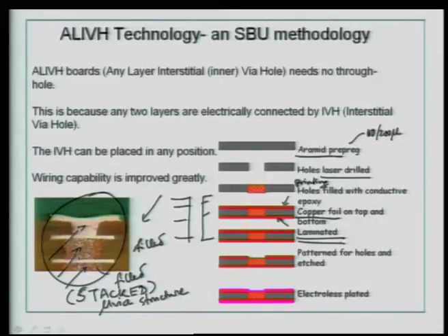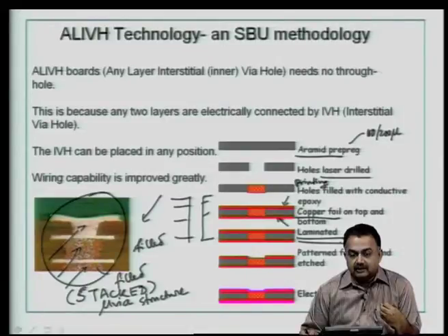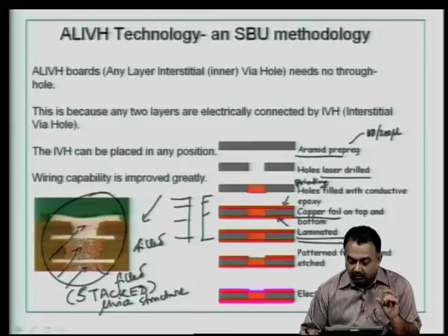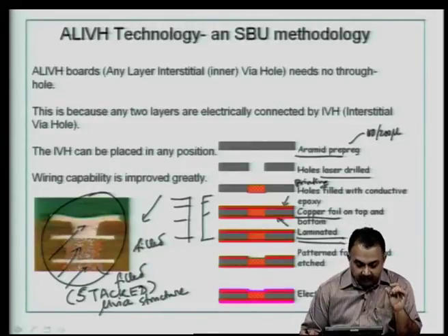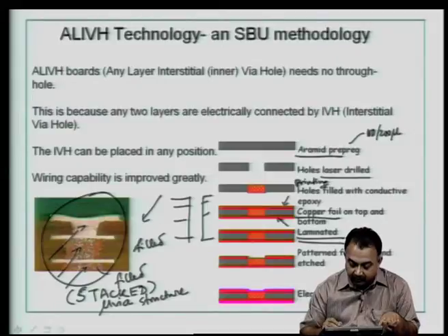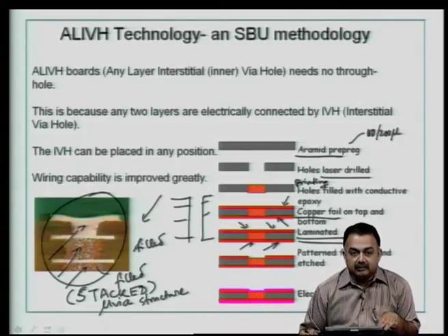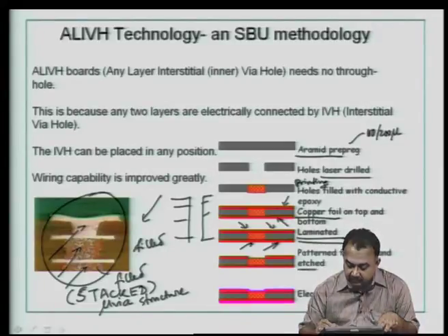Okay. So, here you want to cure the material, and you are also using the pre-preg material's physical properties, because it contains some kind of a solvent. It is a B stage resin, as you know, and then you have the uncured conductive paste that has been dispensed in the hole wall. Now, all of these entities together are laminated. Now, you get a very good bonding between the conductive paste, the pre-preg and the copper at the top and at the bottom, and you get a very rigid laminate structure. So, now this is very suitable for patterning and etching out.